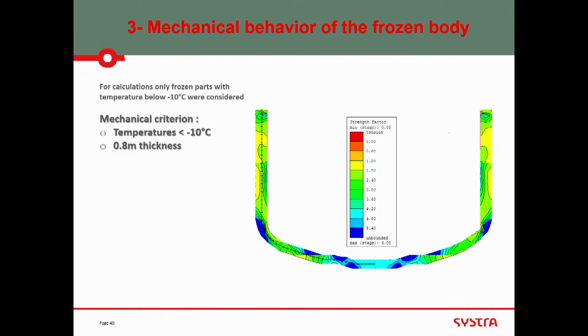So this is what the structural analysis, the strength of material and safety on strength of material, was giving. In this kind of soil, in this kind of project, we consider that the resistance of the frozen soil starts with temperatures below -10, and everything below -10 is considered at -10. So the thickness anticipated is a minimum of 80 centimeters at the end: 80 centimeters for excavation and 80 centimeters for water tightness.